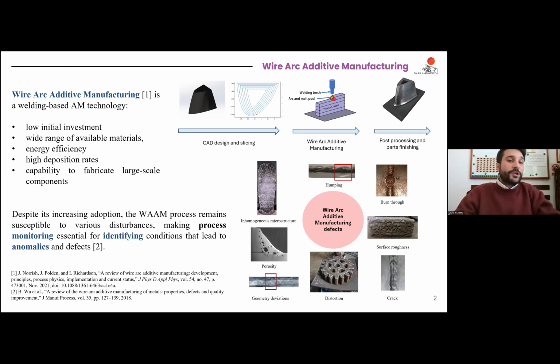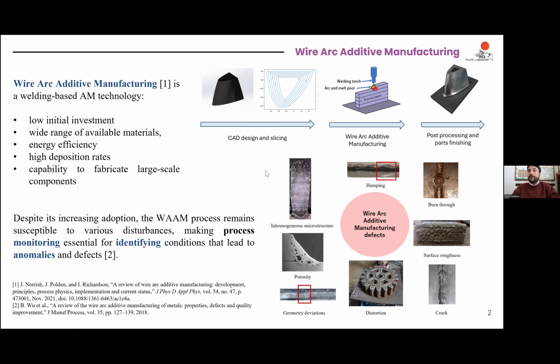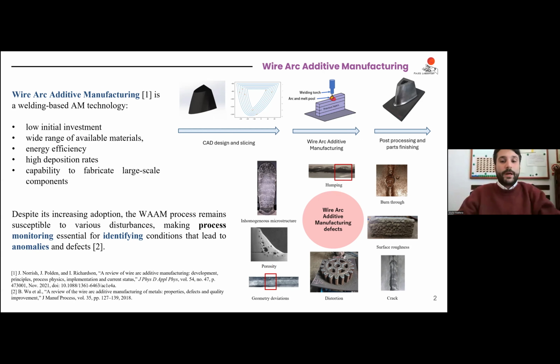It is an energy efficient process because most of the power energy that you are supplying is converted in heat that at the end is going to melt the wire and to print the component. Here with this technology, you can have really high deposition rates because compared to powder bed fusion, you can have also 5-6 kilograms per hour of deposition rates. That is something incredible, right? And this allows you also to fabricate large scale components in a reasonable amount of time.